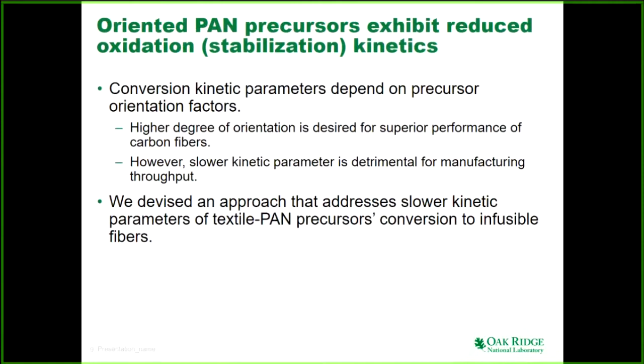Historically, we have learned that if you have a fiber with a higher degree of orientation, when you have stretched it too much, it will show slower kinetic parameters. It will not tend to oxidize that fast. So we are creating a problem for our future, right? We are making oriented fiber because of higher throughput. We made good, stronger fiber. It can tolerate higher stretch for our subsequent higher performance goal, but my kinetic parameters are slowed down. That's because of the high alignment, and during oxidation, molecules need to relax and shrink. So it has resistance to shrink, and that's why the kinetic parameters are slower.